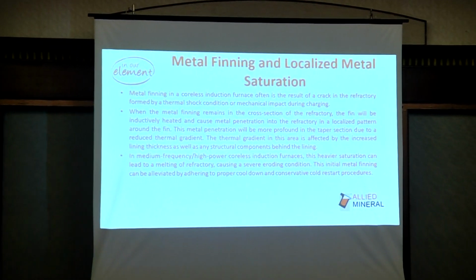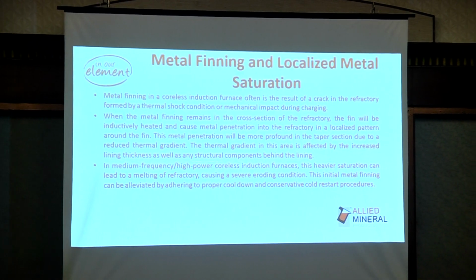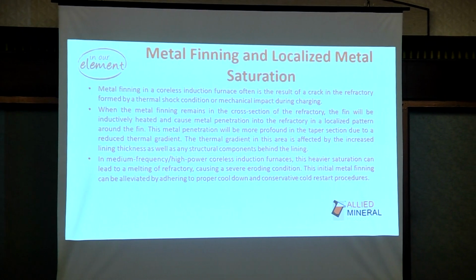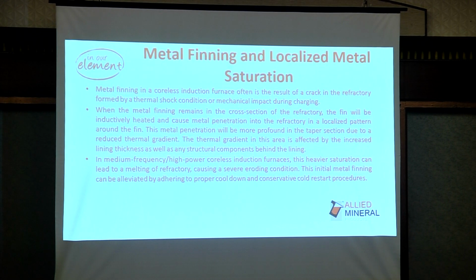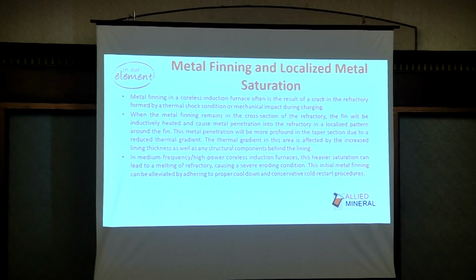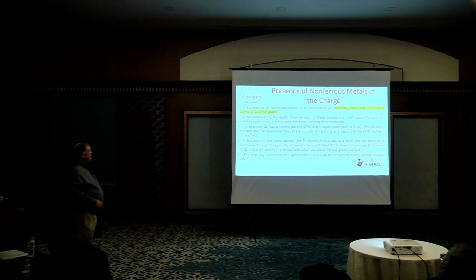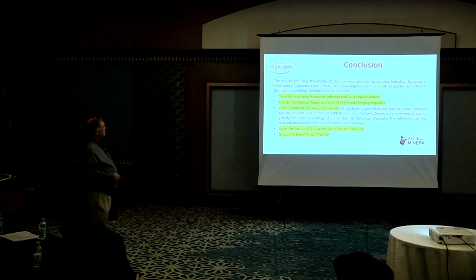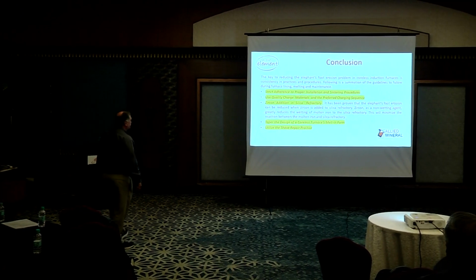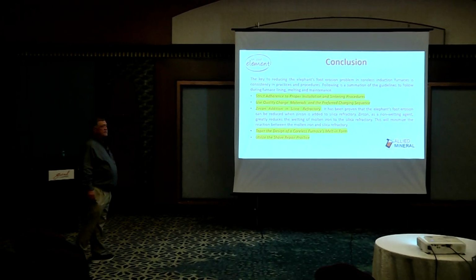So anyways, finning is an issue, and the reason it happens in the bottom is that that's typically where you get molten metal first. So if you don't use a proper daily heat up cycle, what we call a cold start procedure, then a lot of that is going to take place in that taper section and floor. And once you get a fin, now you're putting tremendous amounts of energy into a very small section of metal. And it superheats all the way up into 3,500, 4,000 degrees quickly. It causes an issue. Again, the presence of non-ferrous metals. So in conclusion, strict adherence to installation, use quality charge material and preferred sequence and sizing.